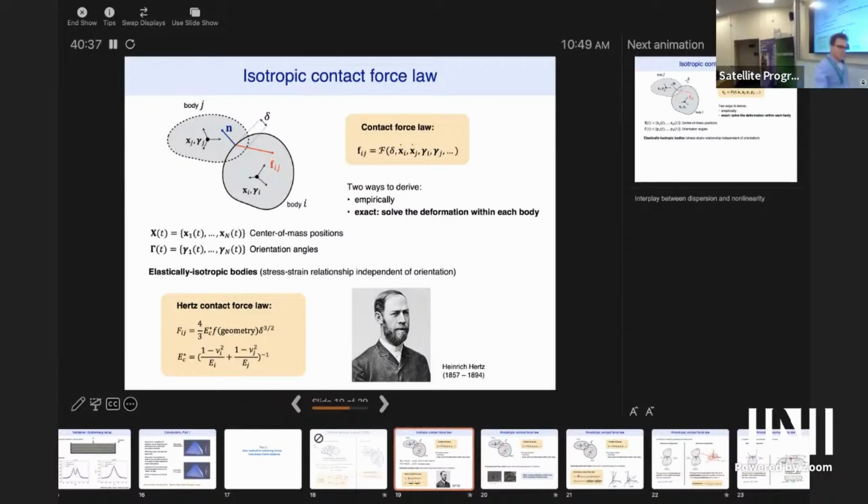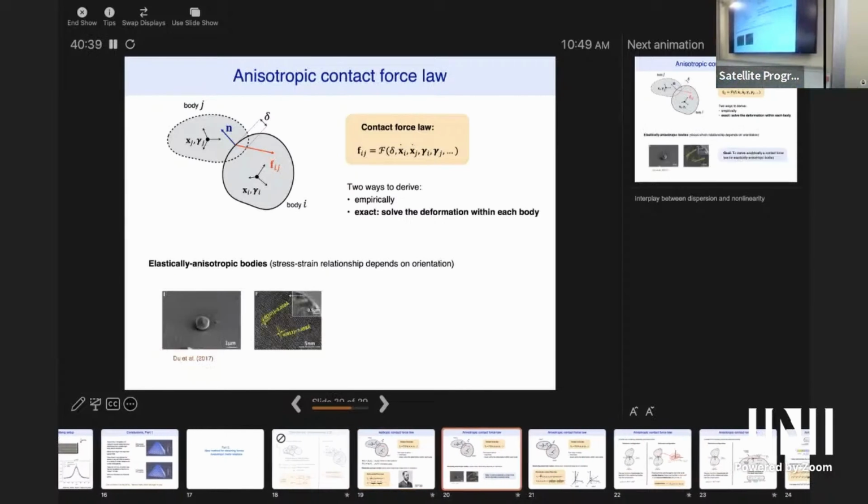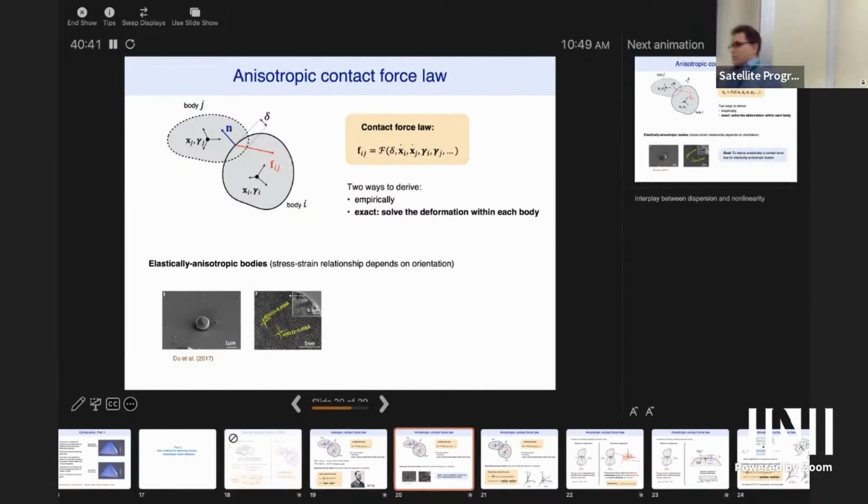So now let me ask you a question. Let's suppose in the world of small, which is where we got into this project, you might start with a piece of polycrystalline metal that looks isotropic. So typical metals are polycrystalline where the crystals are oriented in every direction, so you can just blur it out and say it's isotropic. But let's say I get small enough that each little particle looks like it's one crystal. Okay. So now the elasticity formulation that I would use for that particle is no longer isotropic. It will have crystalline directions, right?